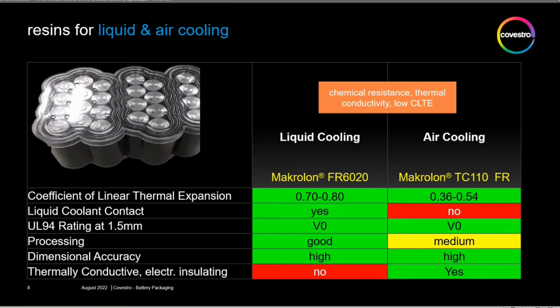Chemical resistance is very important because you don't want the coolant, such as ethylene glycol, to degrade your polycarbonate. Then you would just get a big mess. You need to have good dimensional stability and good hydrolytic stability as well. So for that, the material that we recommend is Makrolon FR6020. It has the chemical resistance to stand up to these coolants, and it makes for a very good heat exchange material.